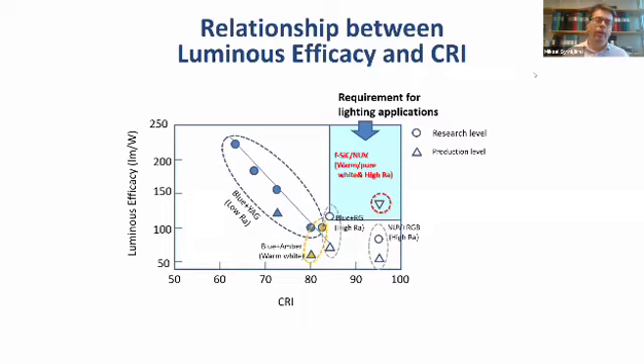And if you compare with the nitride plus phosphor LED, you have the blue, some part of which is converted by the phosphor, and then you have white light out. But in the very efficient LEDs, the blue is penetrating, so you see this blue tone. If you want to improve the light quality to a pure white, you need to make compromises, filters, and so on, and then the efficiency goes down. So silicon carbide has its unique niche. It's not super efficient, but it has this white light.